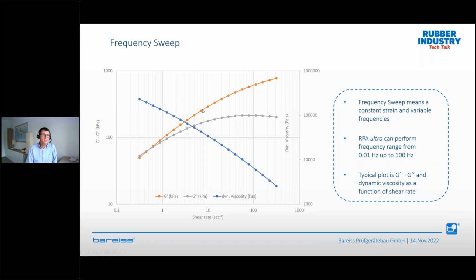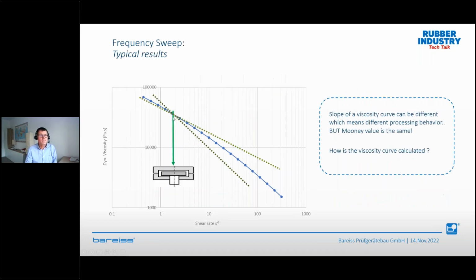The orange one is G prime, the gray one is G double prime as a function of shear rate. And what you see, the blue curve, is the dynamic viscosity as a function of shear rate. Remember, when we performed the Mooney test, we only had this one data point and nothing else on information. This is what I want to show here. Why is it so important?